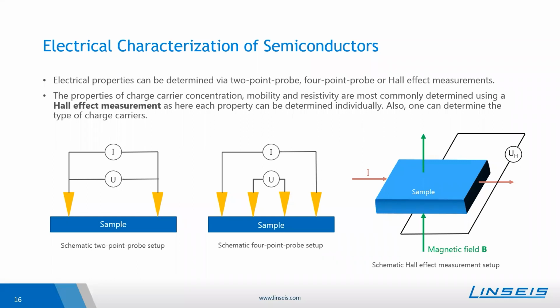Furthermore, the Hall effect measurement setup brings the advantage that one can find out the behavior of the material in a magnetic field, especially as in very strong magnetic fields, one can detect a significant increase of resistivity. This is the so-called magnetoresistance, and this can also be found out with the Hall effect measurement setup.